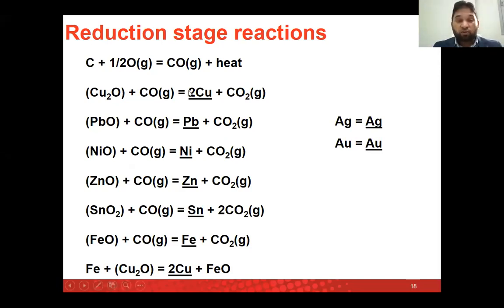So that's why this copper will go into the main phase, the liquid phase. That of course is copper in this case again. And then similarly, we have a lead oxide. Lead oxide will also be reduced with the carbon monoxide. You will get the lead. Similarly is the reaction with all the other elements.